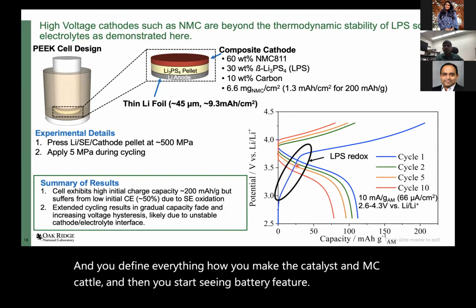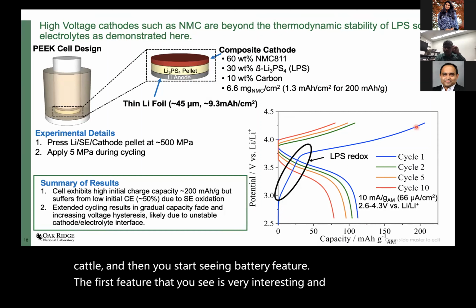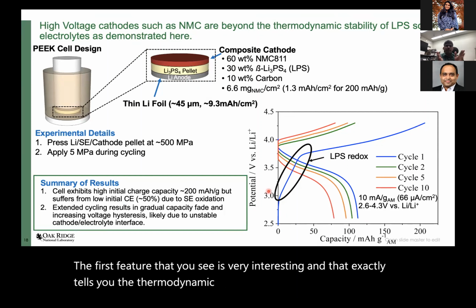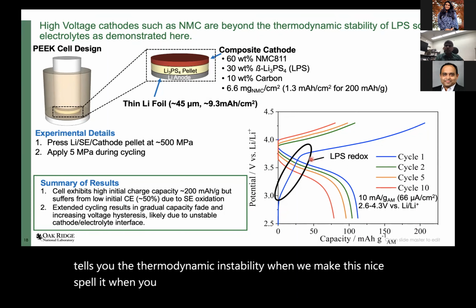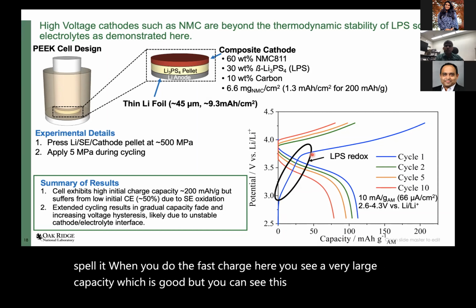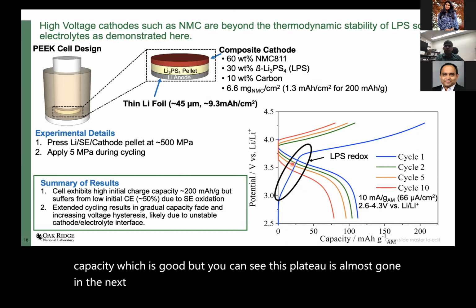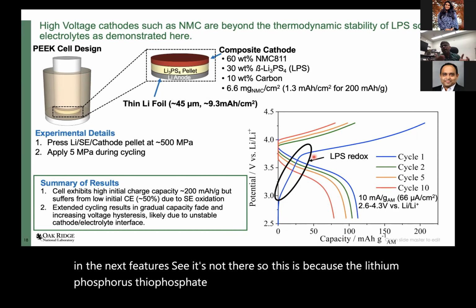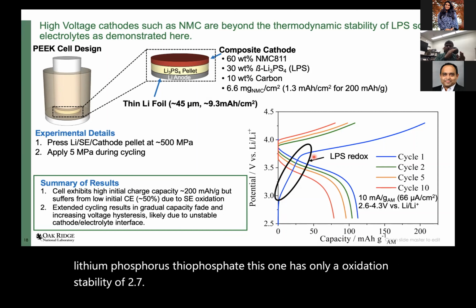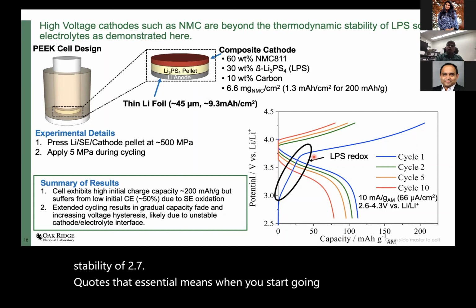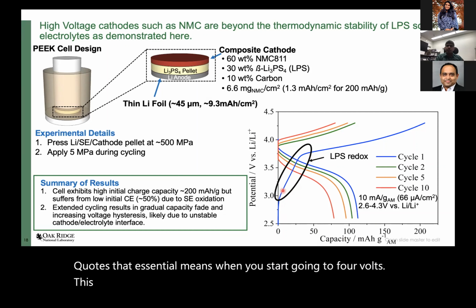Now the first feature that you see is very interesting, and that exactly tells you the thermodynamic instability. When you make this nice pellet and do the first charge, you see a very large capacity, which is good, but you can see this plateau is almost gone in the next cycles. This is because the lithium phosphorus thiophosphate, LPS, has an oxidation stability of only 2.7 volts. That essentially means when you start going to 4 volts, this LPS dissociates. And this extra capacity is an irreversible process that's called LPS redox.